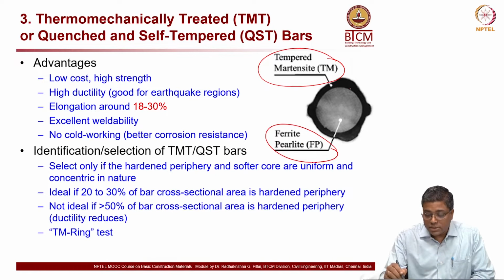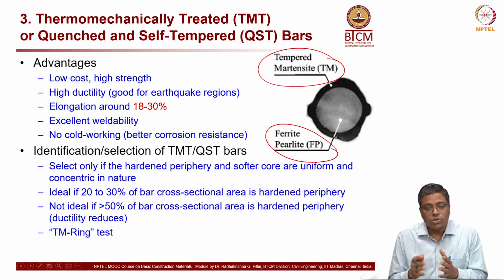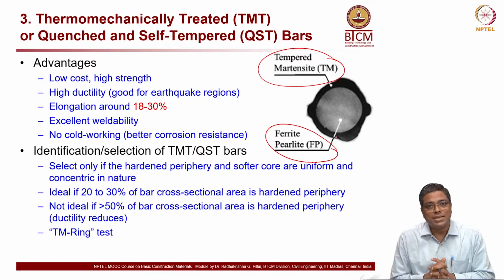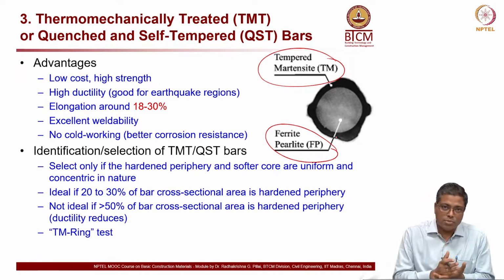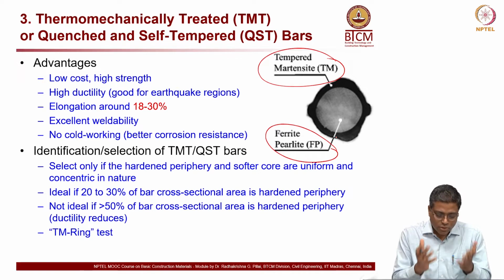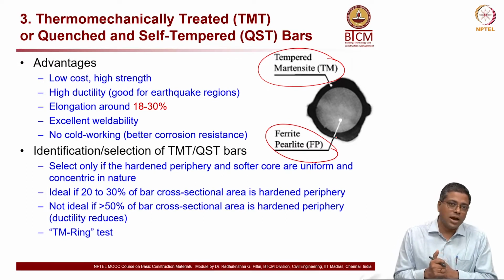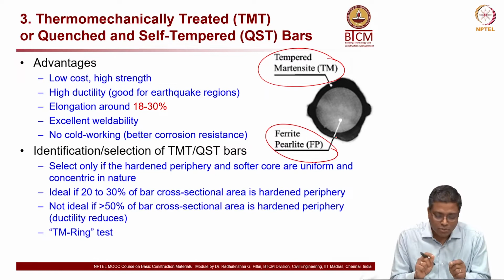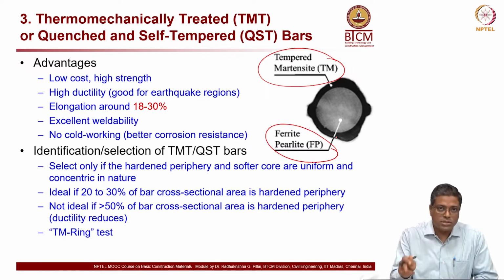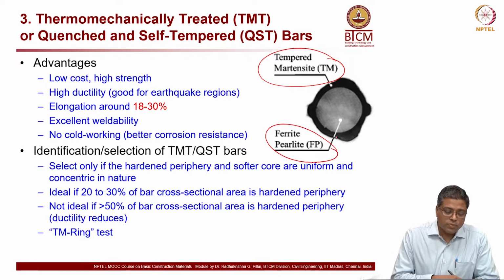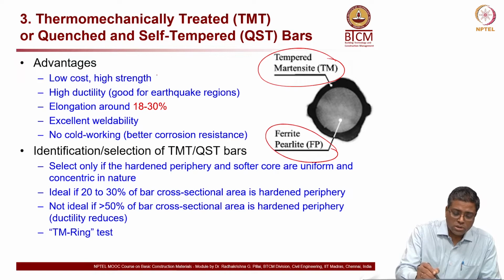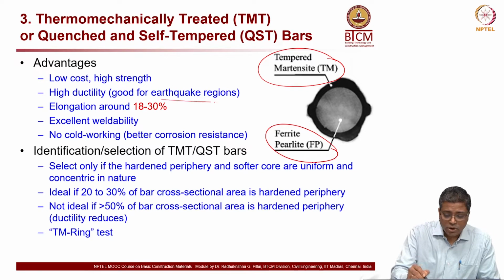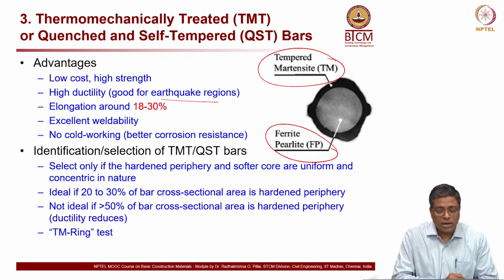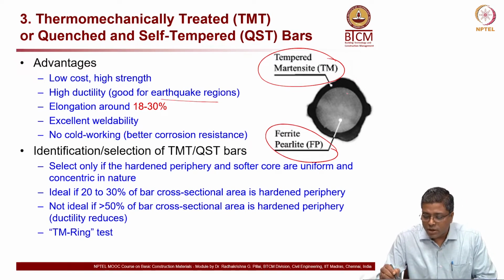Okay, and this color here is not any Photoshop or anything. This is how you will actually see the bar. If you cut the rebar and then look at it with your naked eyes, you will actually see this color difference. With some acid treatment, I'll show you that later, but you can actually see this on all the rebars if they are good TMT bars. Now, what are the advantages of this bar? Low cost, high strength, high ductility. For earthquake resistant regions, you need very ductile rebar. Where is the ductility coming from? It is coming from this part, the ferrite pearlite.